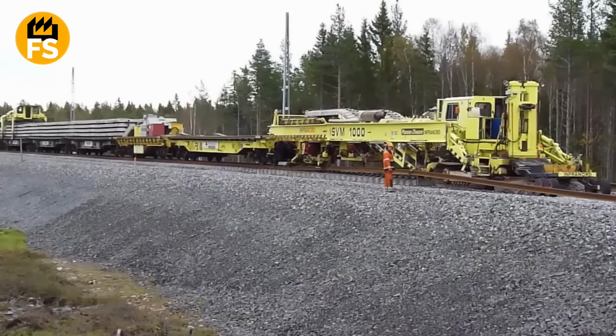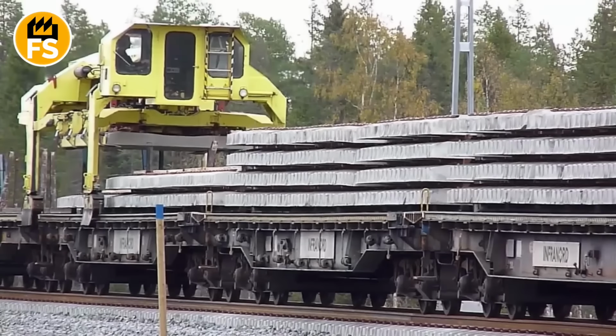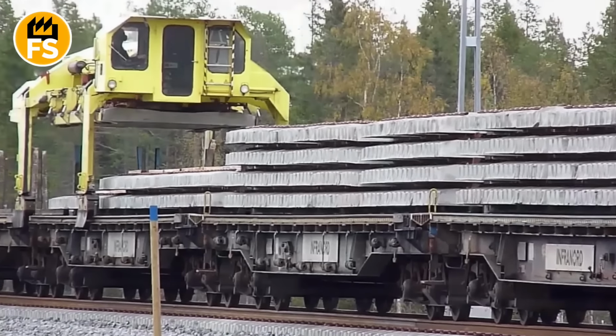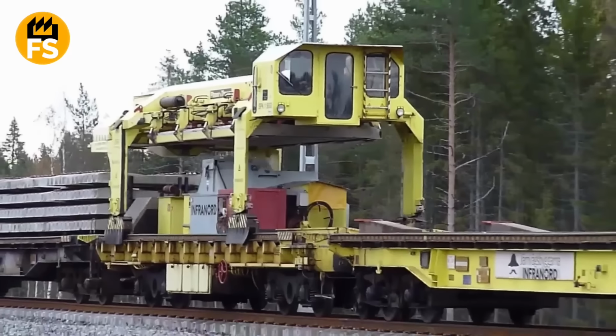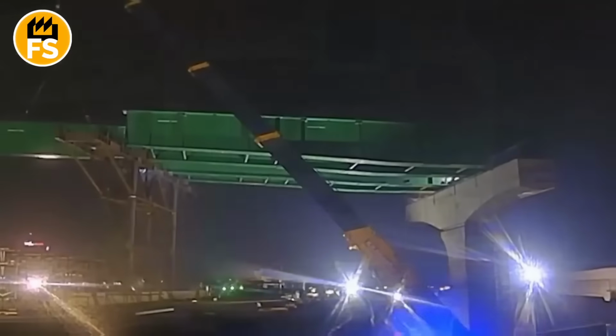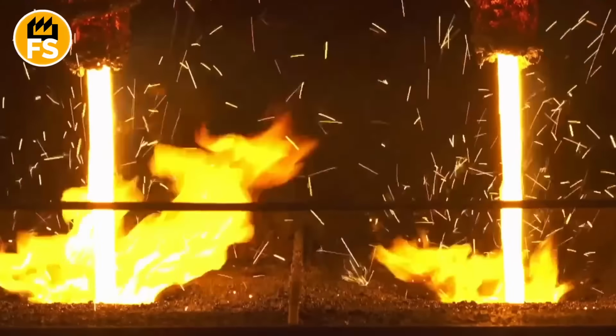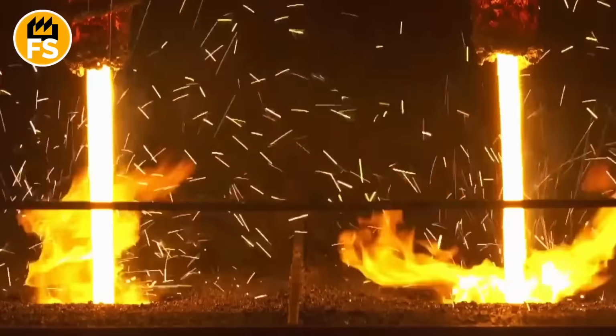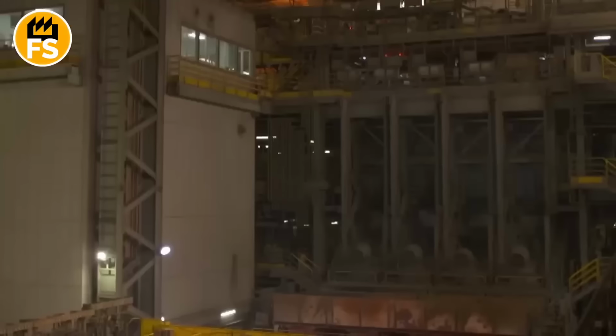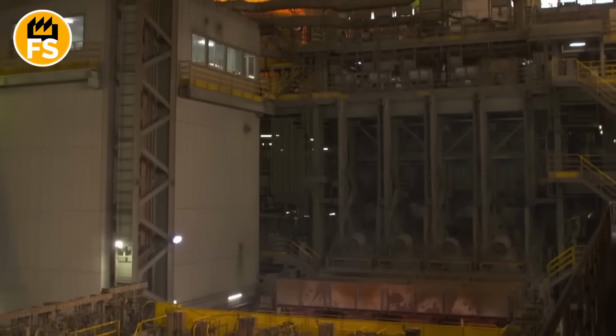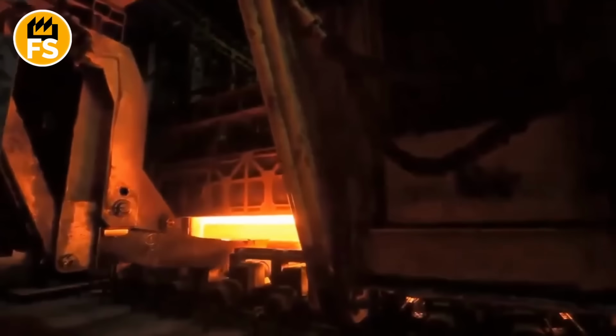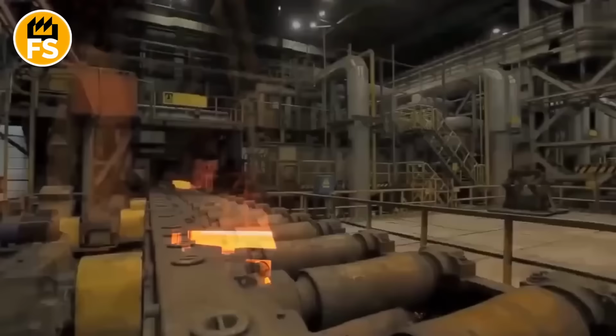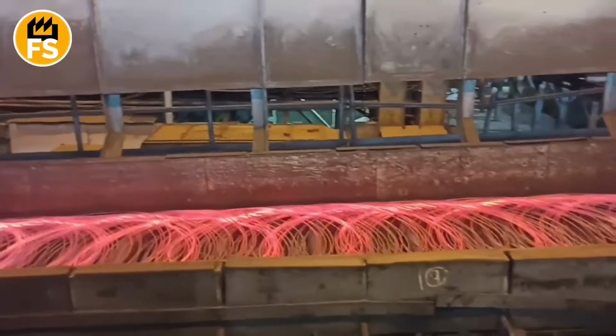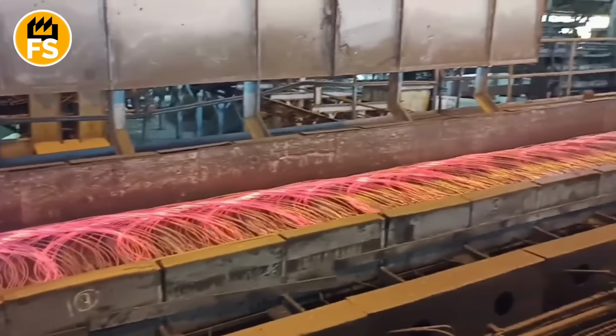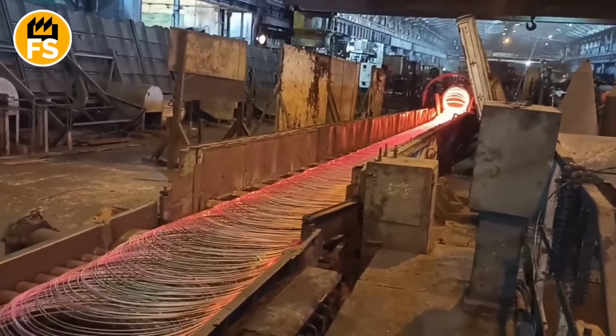work outdoors for decades. The metal is delivered to the factory in the form of huge steel slabs, plates 10 by 2 by half a foot in size and weighing up to 10 tons. They are heated in furnaces to 2,200 degrees Fahrenheit until the steel becomes malleable, almost like rubber. Then these red-hot billets are passed through rolling mills, turning them into long, thin rods with a diameter of approximately 0.25 inches. These are called wire rods.